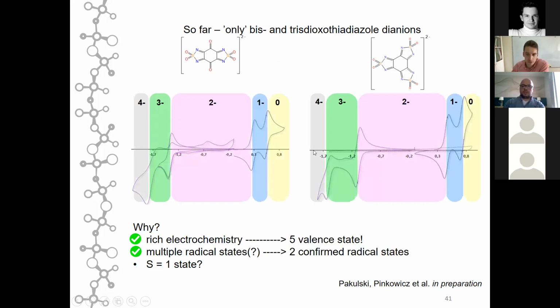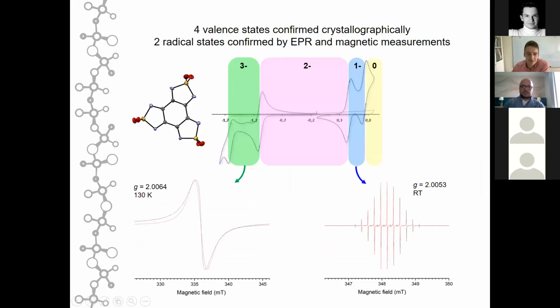You can see that there are 5 valence states possibly accessible in these molecules, and 2 radical states with an odd number of unpaired electrons, which leads to spin 1/2 systems in the case of 3- and 1- molecules. And this we have actually confirmed for the 3- dioxothiadiazole compound like this one. So this is the pure spectrum for the monoanion. You can see the coupling of the spin with the nitrogen atoms, and here you can see the spectrum of the trianion. It's featureless.